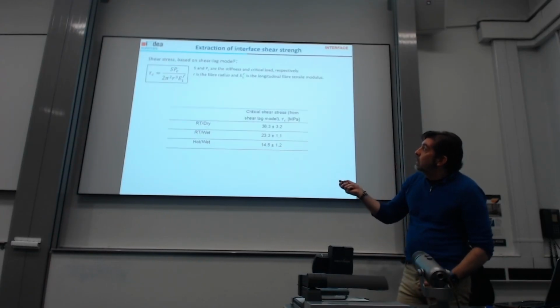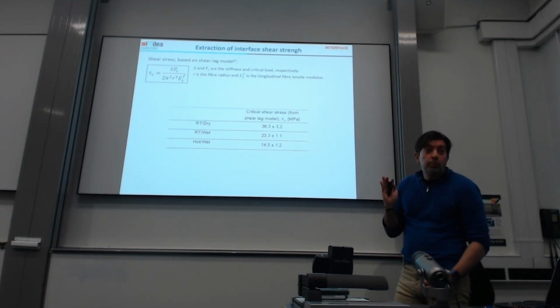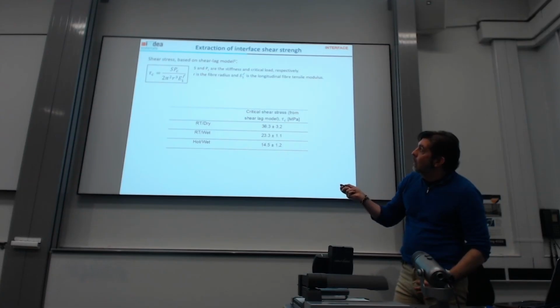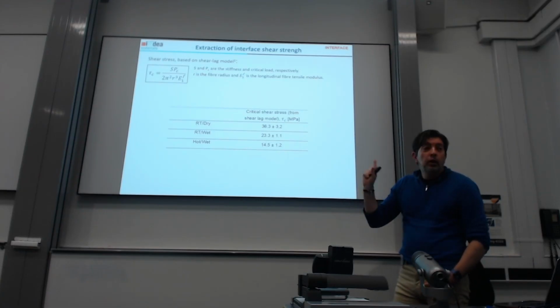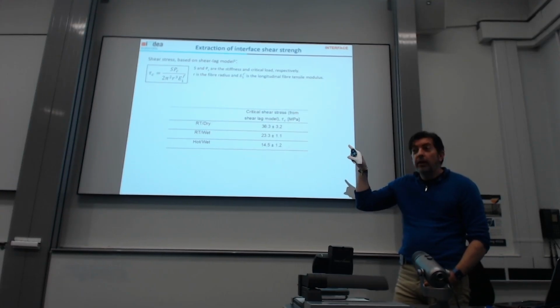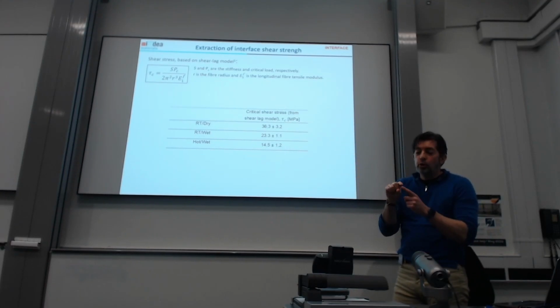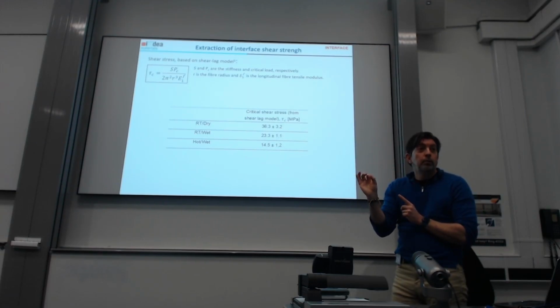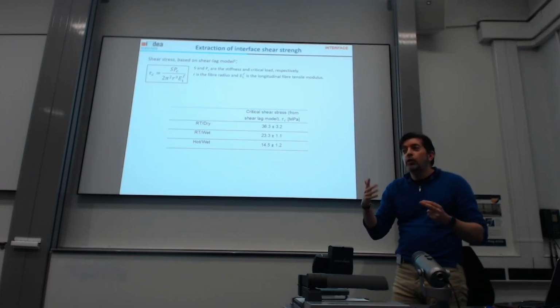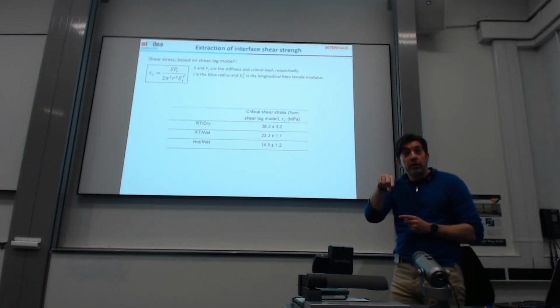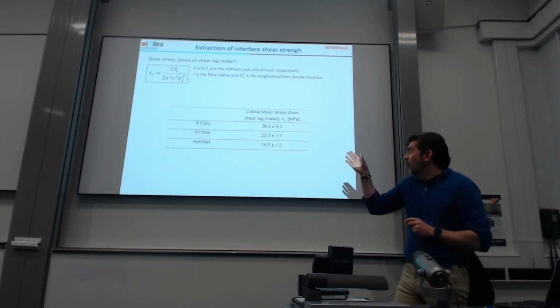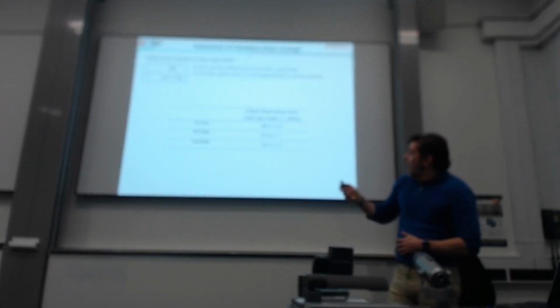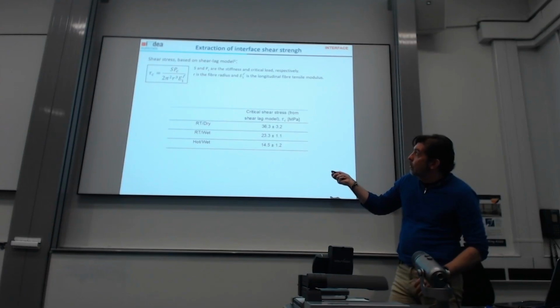Now, we can use this shear lag model to get the shear strength of the interface. As I said, this is a first approximation. Stiffness, critical load, the radius of the fiber, it goes to the cube, so you will get very high errors. Ideally you should measure the diameter of each fiber that you pushed in, because they have different diameters. They can tell you it's 6.85, but then you can find fibers which are 5 microns. I have taken just an average value, but it goes to the cube, so be careful with that. And this is the shear stress you get from this model.